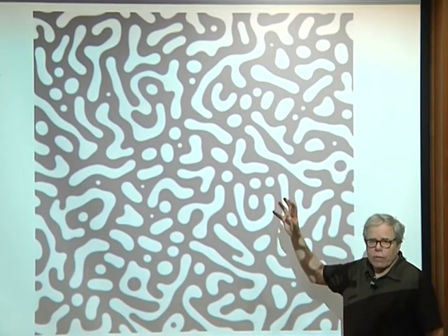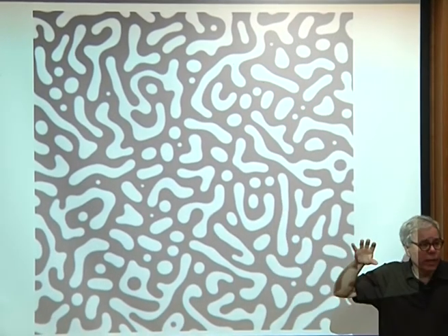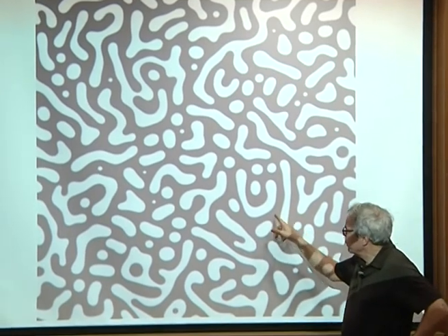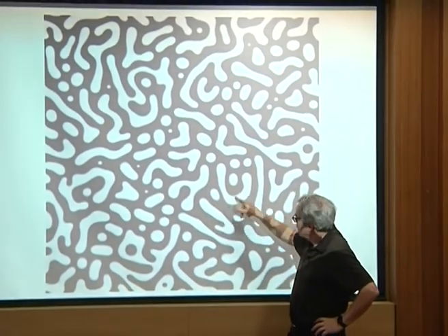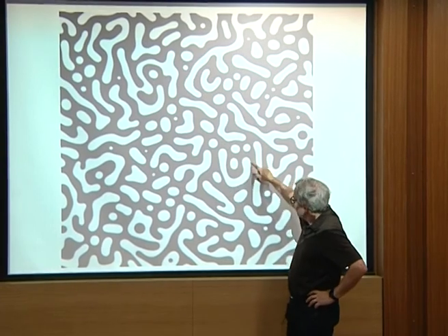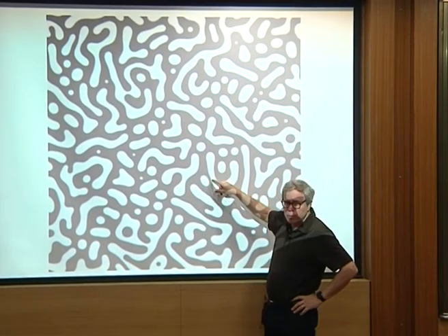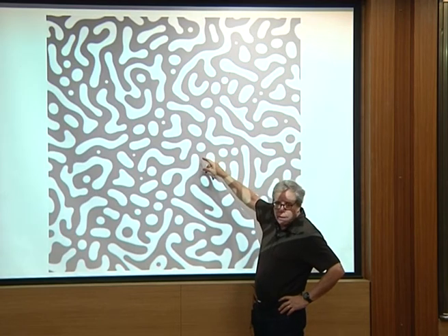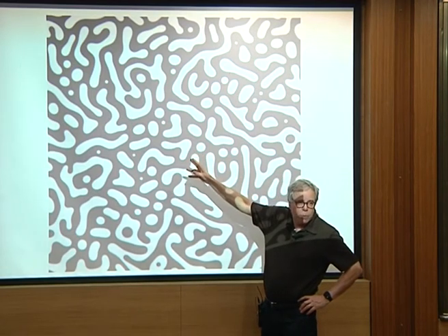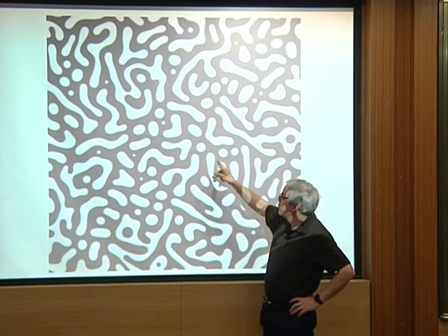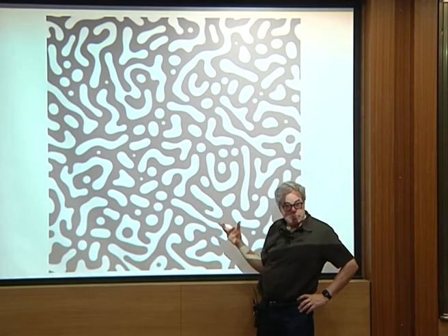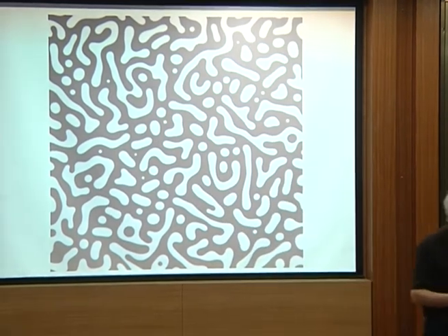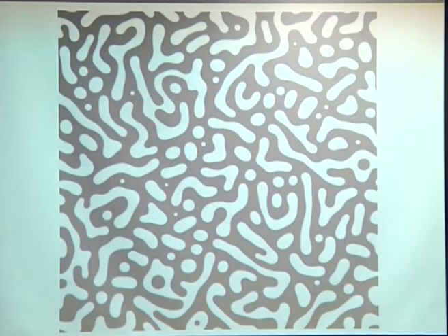If you wanted to solve this using a sharp interface model, like I sketched at the beginning, you'd solve a diffusion equation in here, a diffusion equation in here. You'd mesh up this boundary, put mesh points on the boundary, and measure the curvature of the boundary, and that would set the Gibbs-Thompson equation, or chemical potential at the boundary. You'd have to do this in all the boundaries, and then you'd have to march it in time. And that's why the sharp interface model basically died.